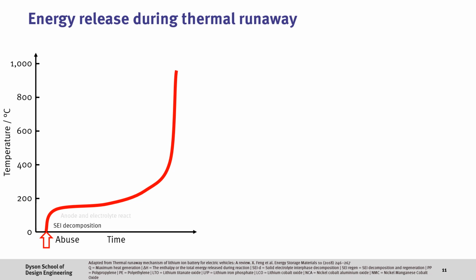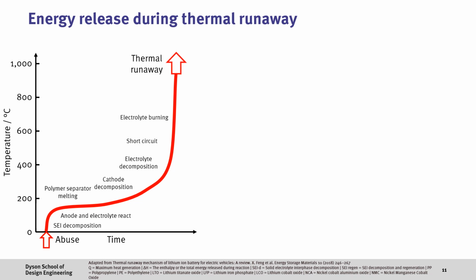So, if we were then to view all of these processes, we can see that we start with the decomposition of the SEI, which leads to the exothermic reaction of the anode with the electrolyte, the subsequent melting of the polymer separator, short circuits, and decomposition of the electrodes and the electrolyte, leading to thermal runaway.